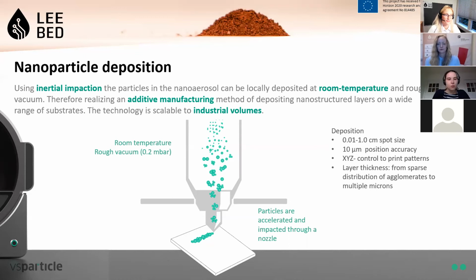A rough vacuum of 0.2 millibar is enough to impact the nanoparticles, and the substrate that's placed below the nozzle sits on an XYZ stage and can be moved, and thus the print can be controlled to create patterns of your desire. Depending on the print speed, we can print various layer thicknesses, from submonolayers up to multiple micron thick layers.